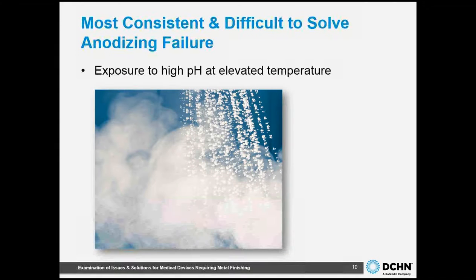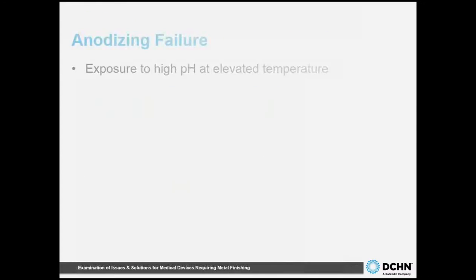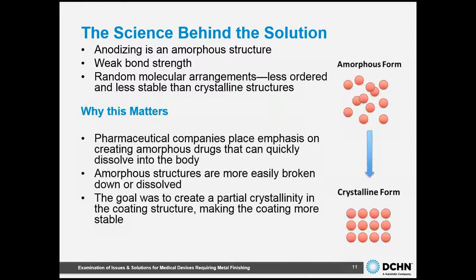But really, let's not get hung up on that. The real point I'm trying to make is that for anodic coatings, high temperature and high pH are the most damaging. Well, why is that so? The truth is, as I stated earlier, under these conditions, anodic coatings will eventually be dissolved because traditional anodizing is an amorphous coating. So that's game over, right?